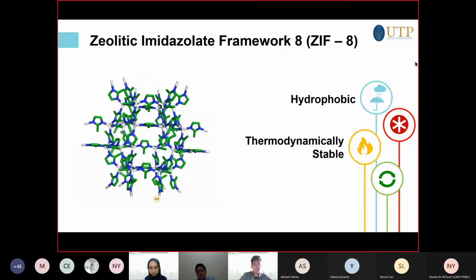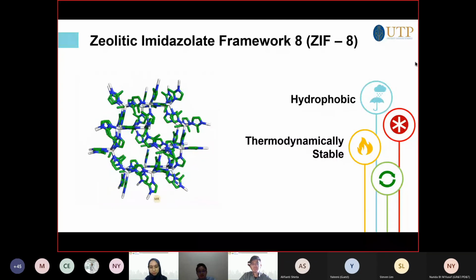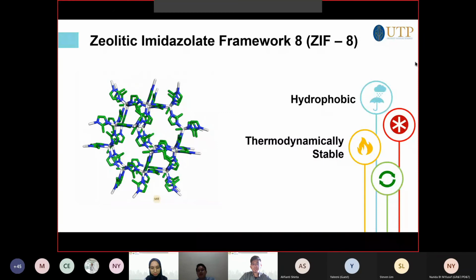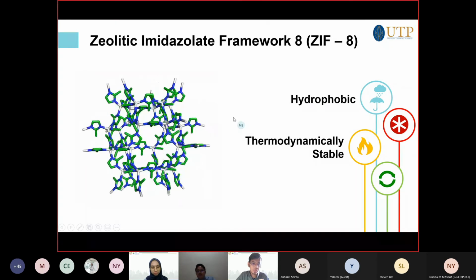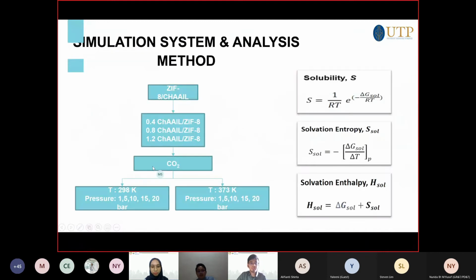Impregnation of choline alanine inside the zeolitic imidazolate framework 8 modified the nanocageous environment of the pores, leading to the augmented adsorption of carbon dioxide. Apart from the pore modification executed by the impregnation of choline alanine, the hydrophobic property of zeolitic imidazolate framework 8 is another crucial property that ensures no interference from the incoming water vapor during the carbon dioxide adsorption process, which could jeopardize the integrity of the composites and may lead to a reduction in adsorption capacity of the composites.